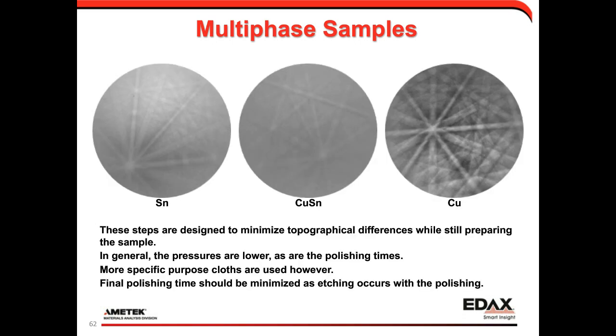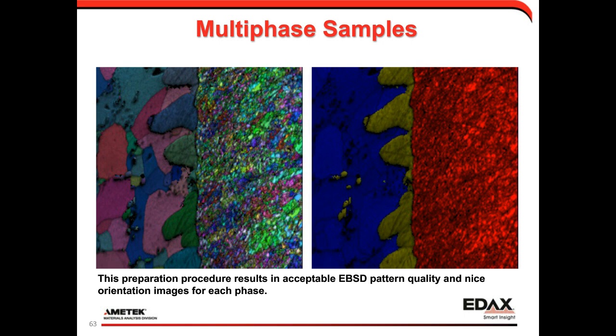So when we look at the patterns from each phase, you see we get indexable patterns from each. They're not perfect patterns from each one, which we'd generally like if we were looking at a single-phase material, but they're usable patterns for each phase. A lot of times for multi-phase samples, we need to minimize the topography that's introduced while still getting usable diffraction patterns. So the pressures are lower, the polishing times are less, with specific cloths for specific types of materials and specific removal rates, and we're trying to minimize the final polishing time with colloidal silica to minimize differential etching rates with the colloidal silica medium. This shows on the left the orientation map, and on the right the phase map from that interface in the solder material. Using this approach, we still get very nice usable results with EBSD mapping.